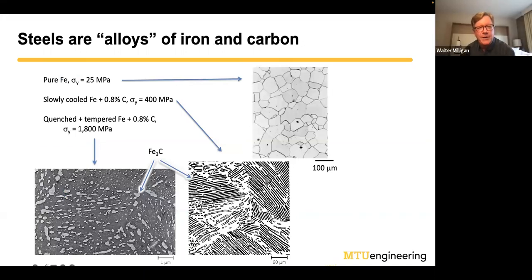Anyhow, here is an example of 2 different materials. The one on the upper right is a microstructure. I can't get into how we make this, but it's a picture of the microstructure of pure iron. The only thing we see are these black lines, and these are grain boundaries. Metals have grains just like wood does. Each one of those individual round blobs is a crystal that has a given orientation, and the interfaces between them are the grain boundaries, but there's no second phase in there. Because of that, it has a very low strength.